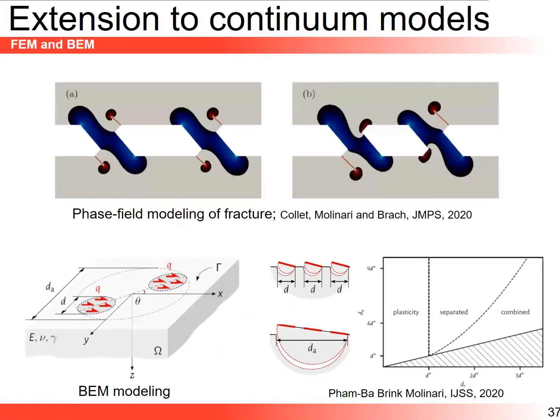Okay, it turns out there is a lot of interesting perspective also to extend this to continuum models. And here I'm turning to a very nice paper that Stella has led when she was at Caltech with a student, Sylvain Collet, who worked with her at Caltech. And in this paper, she's using phase field modeling of fracture to precisely look at this, except that with the phase field modeling approach, you can probe a material parameter space which is much richer and much more precise than what you can hope to do with atomistic simulation, where it's hard to change the plastic properties with atomistic potentials, whereas phase field modeling of fracture with a good description of bulk plasticity opens the space for you.